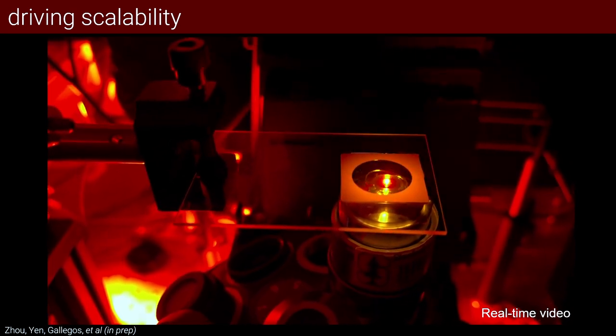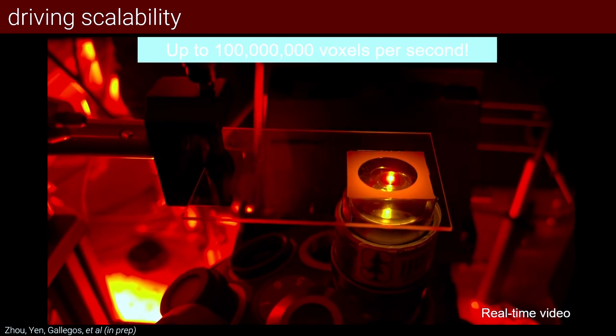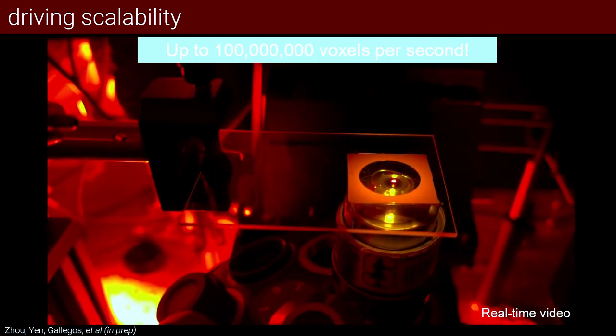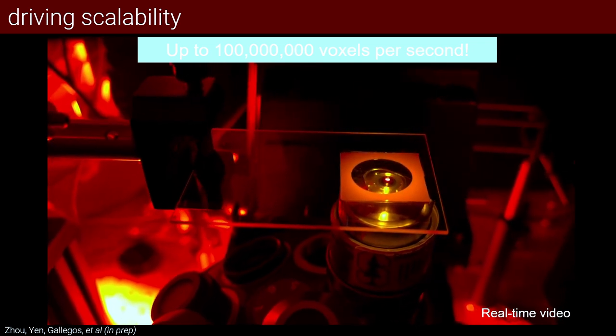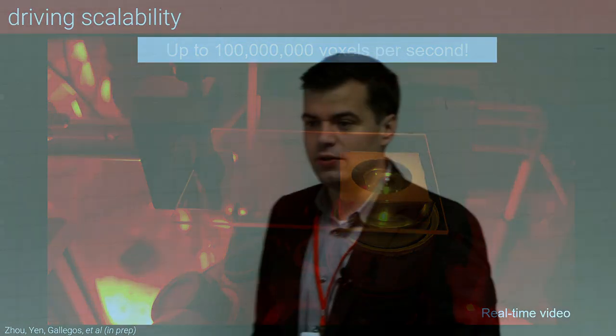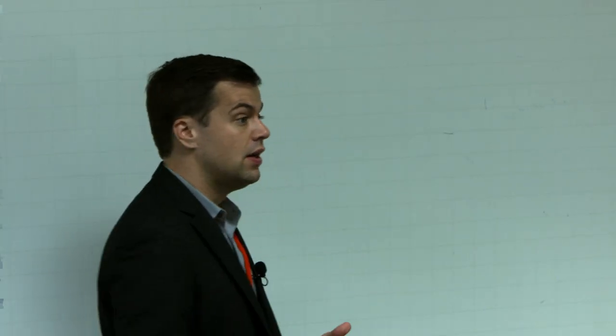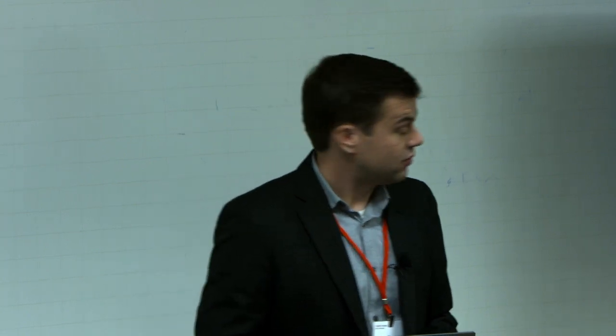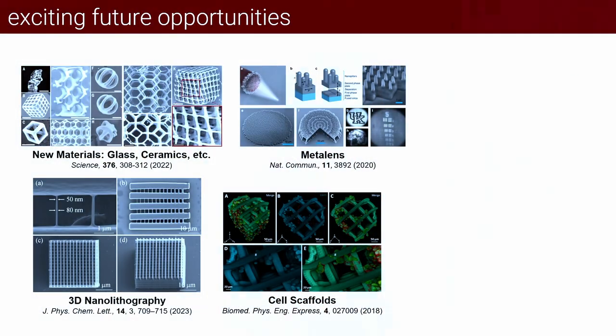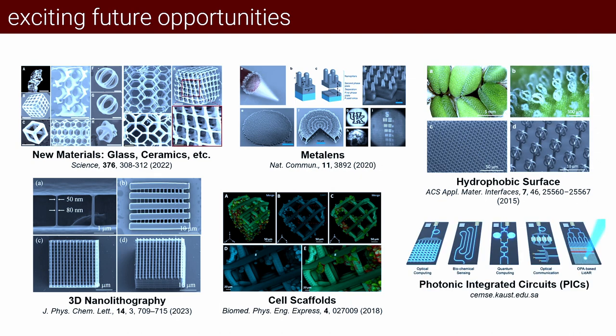And the nice thing is we can move this around in X and Y such that we can move up to about 100 million voxels per second. Which means if we go back to those nanowire prints or those microneedle prints that we were talking about at the beginning, instead of 12 hours, we think using a technique like this, we can get that down to a few minutes. That really opens up opportunities to build these nanostructures over much larger areas, which then opens up new opportunities to use them in a whole bunch of new and exciting fields. I'll just dart through these very briefly, looking at things like optics, bio, and building new surfaces. Okay, so that's the scalability, and we think that's a really exciting area that is up and coming for these types of nanoscale materials.